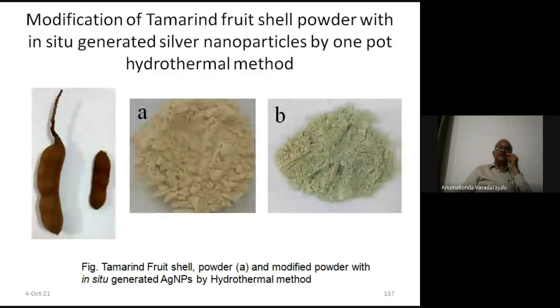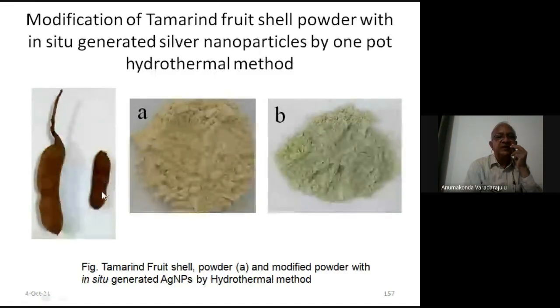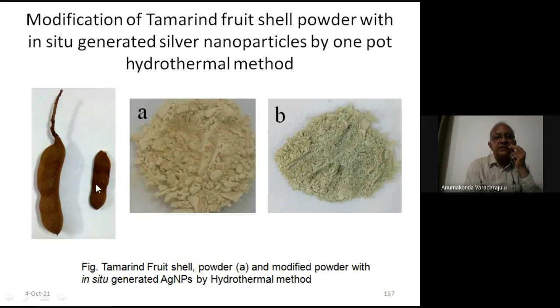Then we modified in similar manner tamarind fruit shell powder. This is the tamarind. The shells we will be throwing away. We want to expand this shell and make it as a powder and use it as a filler for making the polymer composites, low cost polymer composite material. So this is the original unmodified fruit shell powder, and then we generated the silver nanoparticles by one-step hydrothermal method. That means we have taken the silver nitrate solution at 80 degrees Celsius, and then we added this powder and then kept that for about 24 hours. Then the color changed.